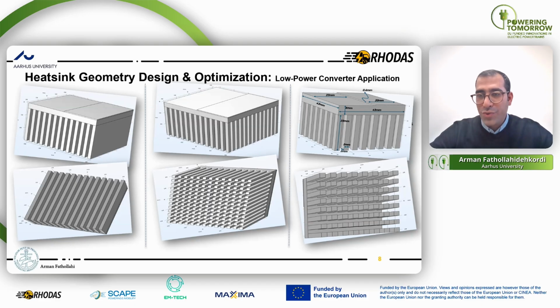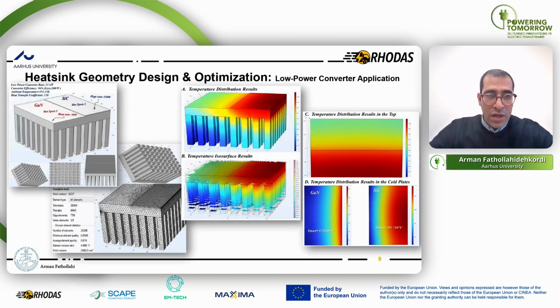We had a step and two different heights in the PCB for the SiC and GaN parts of the low power converter. Because of that, we wanted to minimize the height of the thermal interface material. So we built a step on top of this heatsink, and after that we had different rounds of optimization for the type of fin and the geometry of this air-cooled heatsink.